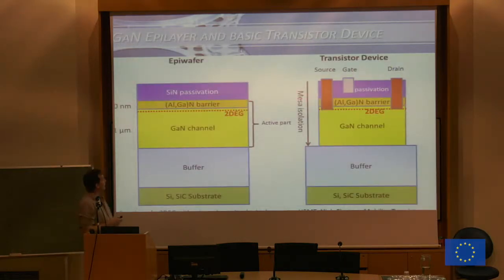Now that we know how such a structure is created, a typical epi wafer will look like this. We start from a substrate, silicon carbide, sapphire, what have you. Here on the top we have this gallium nitride, aluminum gallium nitride barrier configuration that gives you the active part of your device. And in between we will need to grow a buffer. I will talk about the buffer, what the necessities are. Basically what we want to do there is compensate the differences between your silicon substrate and the III-nitride material on top. What's also plotted here is passivation, because passivation is crucial in this technology. I will also say a few words about that.